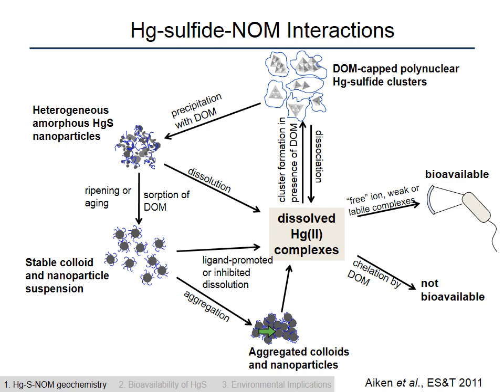Here I'm showing a figure of how that process might happen and how organic matter could influence this process of mercury sulfide precipitation. So imagine you have dissolved complexes of mercury that are starting to precipitate with sulfides. The organic matter can interfere with this process by coating the initial polynuclear clusters that form, as well as coating the amorphous nanoscale mercury sulfide particles that are the nucleation products of mineral sulfide precipitation.